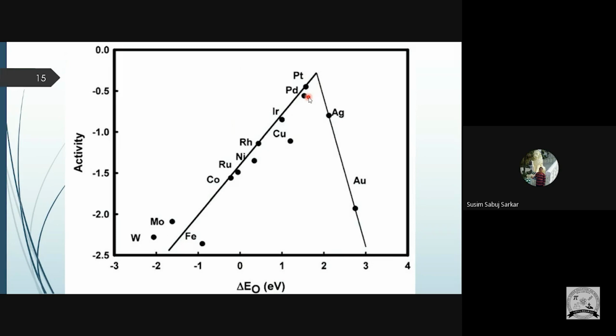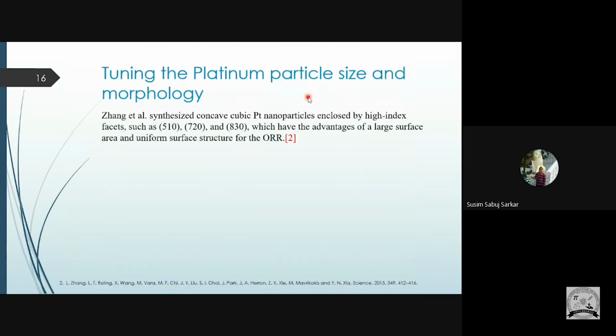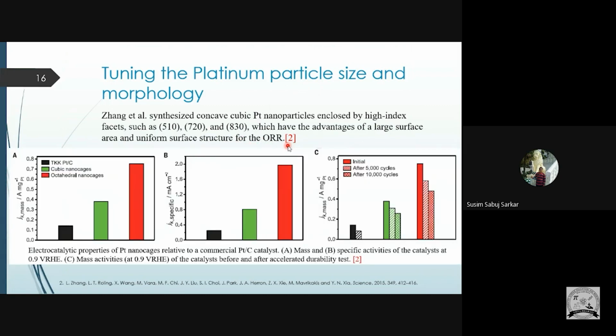Now what people are doing is tuning the platinum particle size and morphology. They synthesized concave nanocube particles enclosed by high index facets, such as (510), (720), and (830). This has the advantage of a large surface area for the ORR. The graph is showing that first of all they are measuring the mass activity of that, against the normal platinum carbon catalyst.